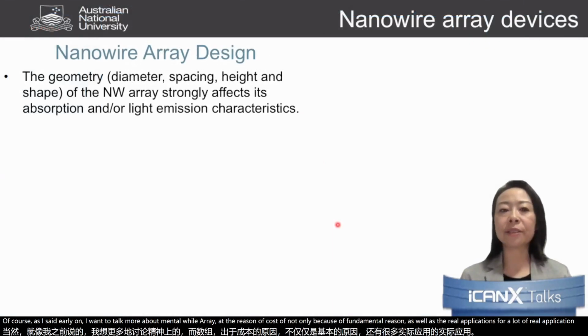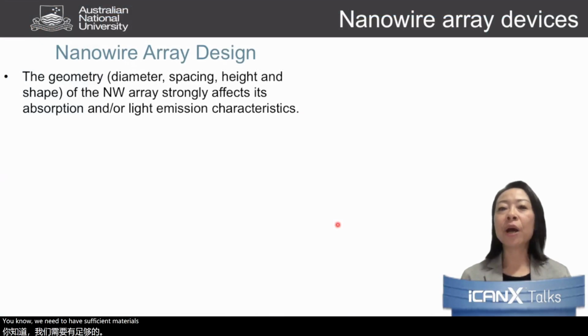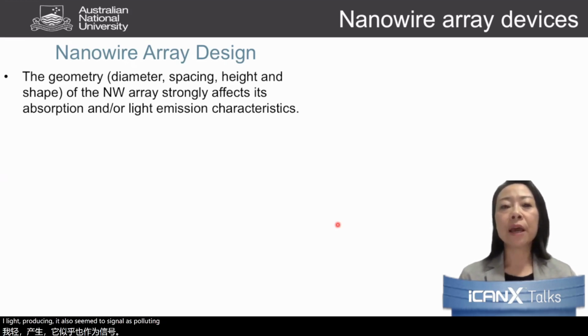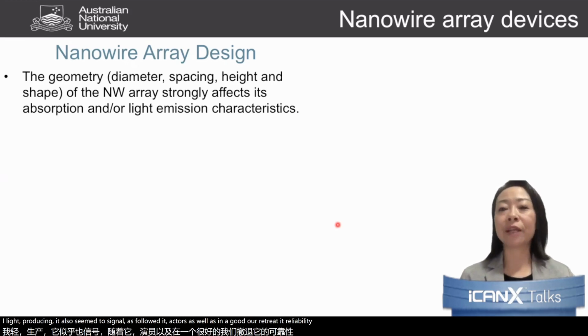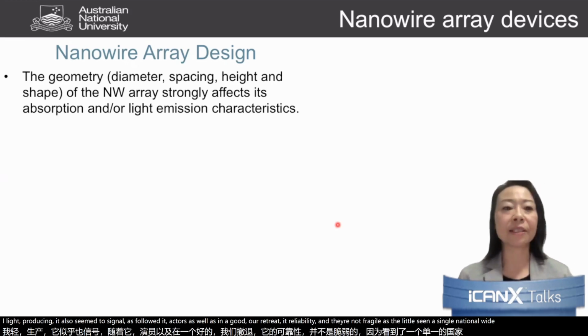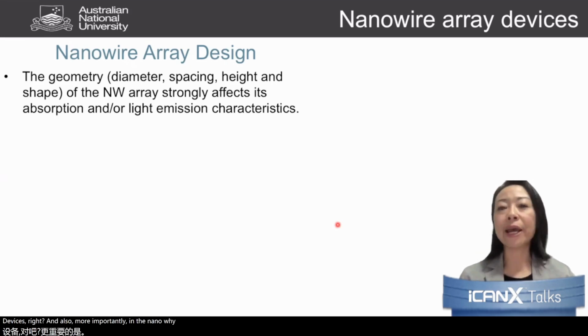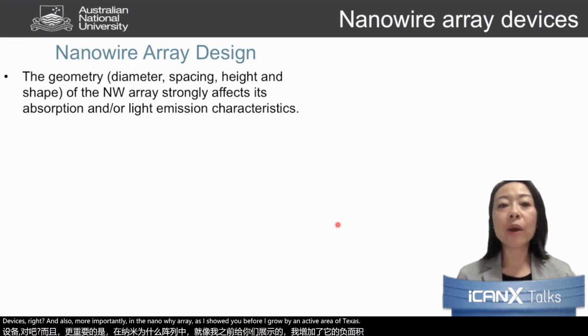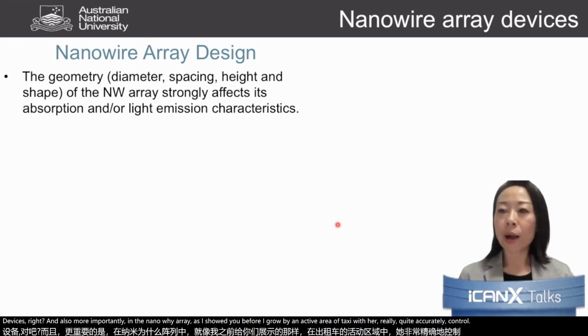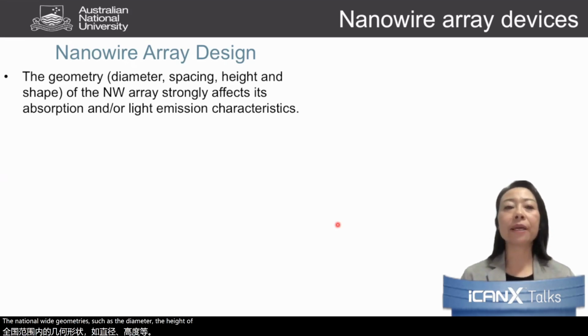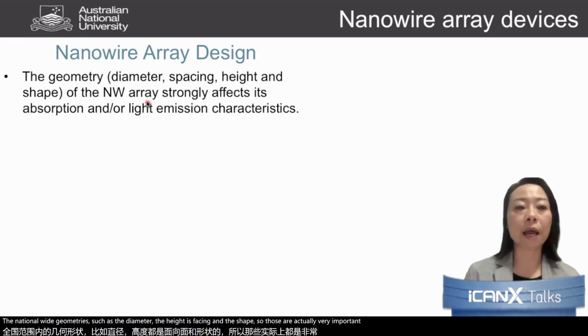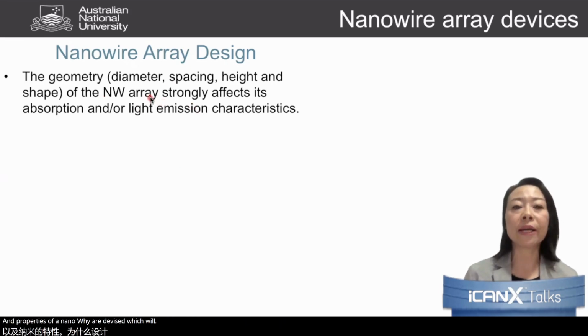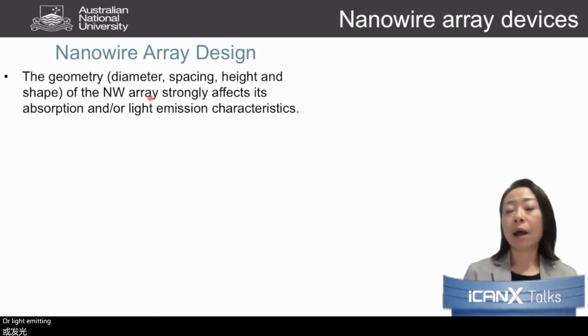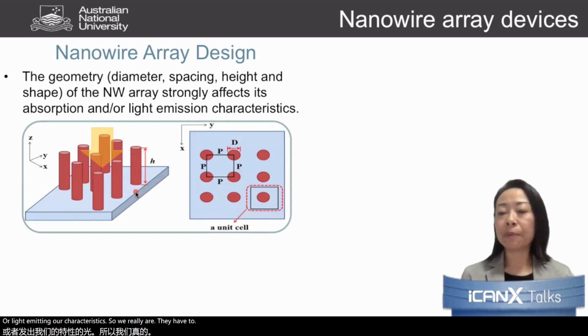For a lot of real applications, we need sufficient material to have a good signal, light produced or good signal as photodetectors, as well as good reliability, and they're not as fragile as little single nanowire devices, right? And more importantly, in the nanowire array, as I showed you before, grown by selective area epitaxy, we can quite accurately control the nanowire geometries, such as the diameter, the height, the spacing, and the shape. Those are very important properties of a nanowire device, which will strongly affect its absorption or light emitting characteristics. So we really have to develop simulation techniques to understand those properties and to optimize our device design.